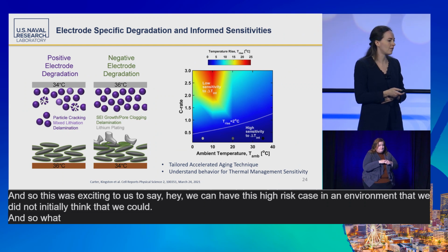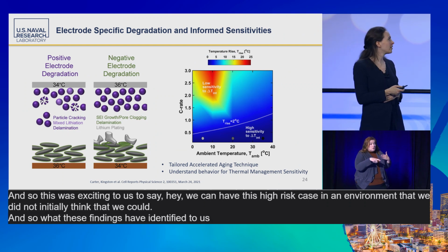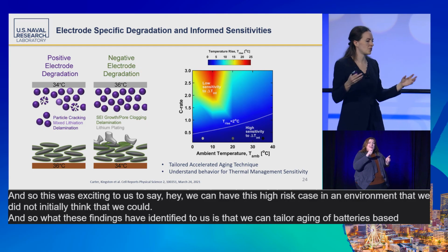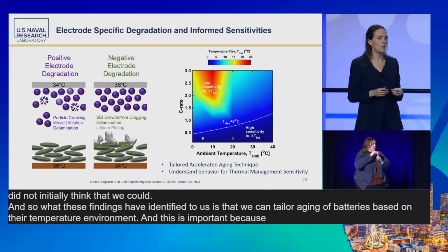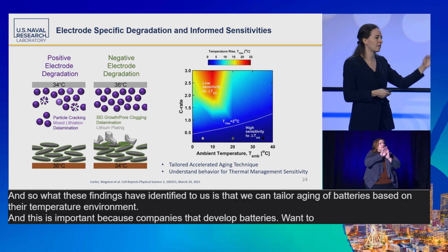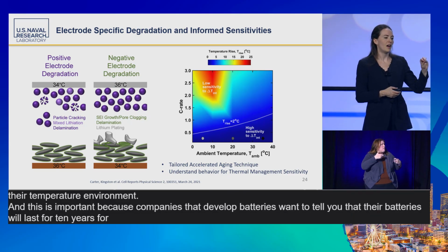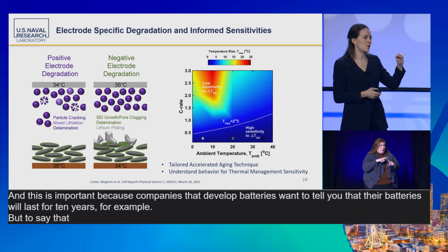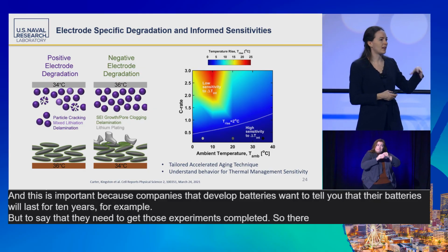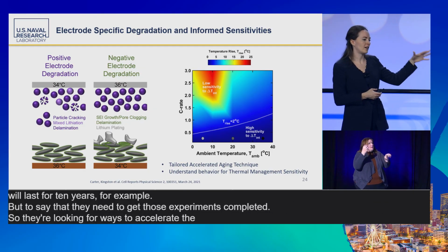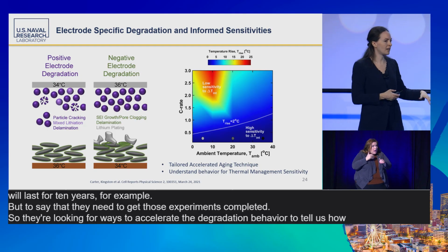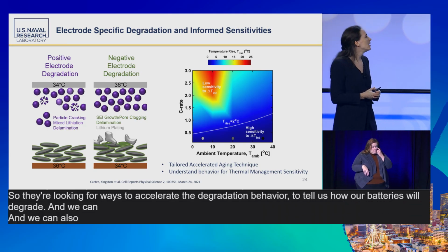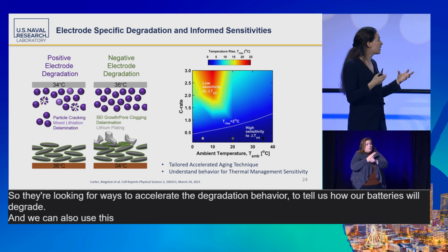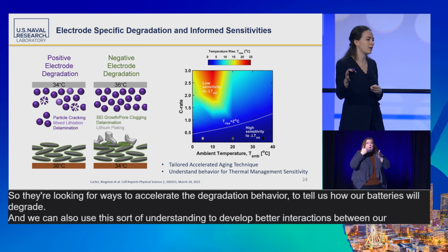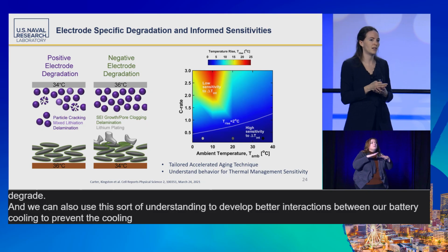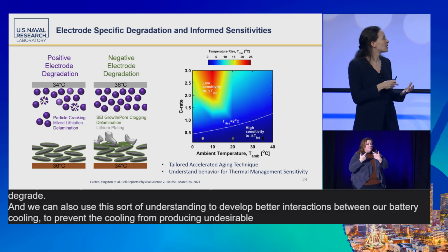And so what these findings have identified to us is that we can tailor aging of batteries based on their temperature environment. And this is important because companies that develop batteries want to tell you that their batteries will last for 10 years, for example. But to say that, they need to get those experiments completed. So they're looking for ways to accelerate the degradation behavior to tell us how our batteries will degrade. And we can also use this sort of understanding to develop better interactions between our battery cooling to prevent the cooling from producing undesirable conditions within the batteries.